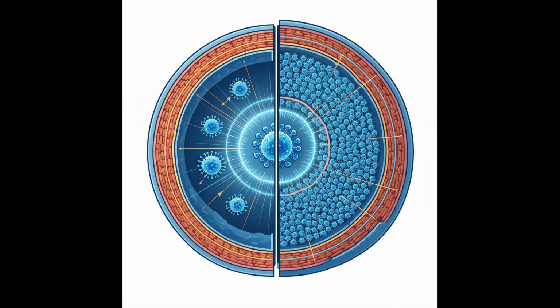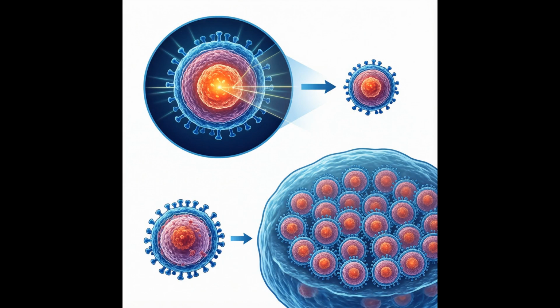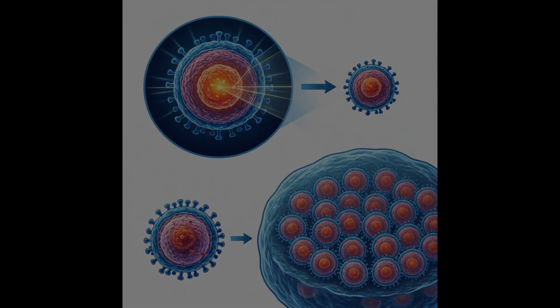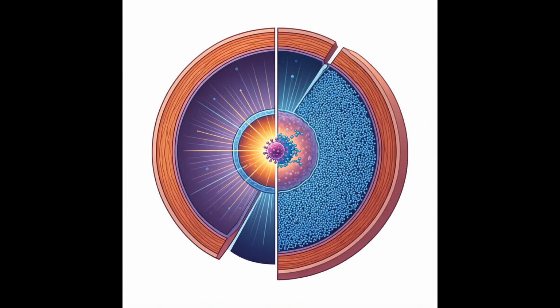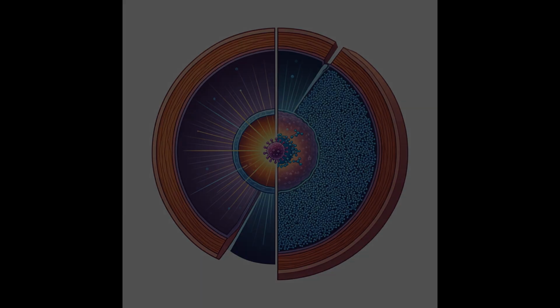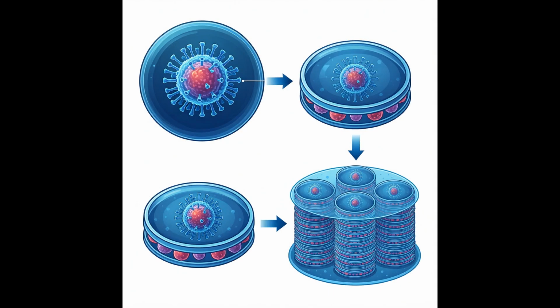The core capability of PCR to detect viral material within minutes relies on a specific mathematical property known as exponential amplification. Unlike linear growth, where one unit adds another, this process doubles the target sequence during every single thermal cycle. Starting with just 2 copies of a genetic segment, the first cycle produces 4, followed by 8 in the second round. By the 10th cycle, we have reached over 1,000 copies from that initial trace amount. This compounding effect means that after 30 cycles, a single molecule can theoretically generate more than 1 billion identical sequences.